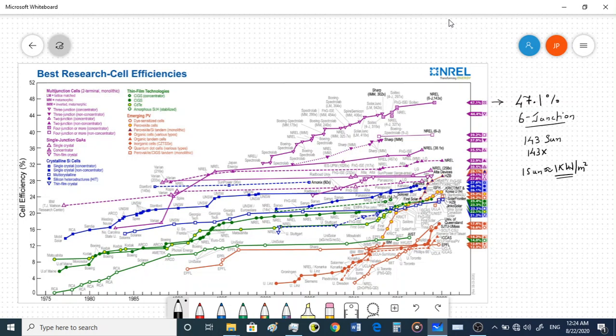Basically these are lenses which can concentrate light onto the cell. They use a light source with 143 times this intensity, concentrated, and shine it onto the cell. From the cell they take the IV characteristics by changing the resistance across it, and from there they calculate the efficiency. It is reported that they have got efficiencies up to 47.1% with a 6 junction solar cell.